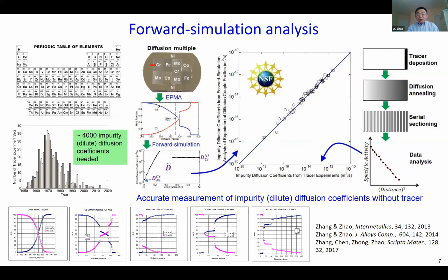So over the years, we developed this method called forward simulation analysis, that instead of doing the Boltzmann-Matano analysis, we basically assume a function and then we use the Darken equation and the diffusion equation to simulate until the match. In this way, we can get a very accurate impurity diffusion coefficient just from the simple diffusion profile that we got from diffusion couples. We have tested this method over a very wide range, more than 130 some elements. So this is a very efficient way of getting impurity diffusion coefficients.